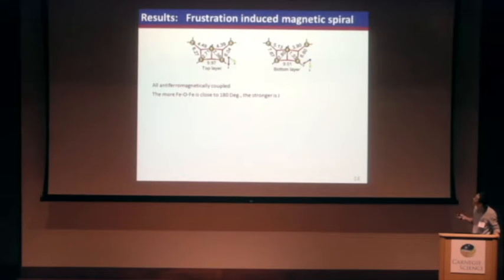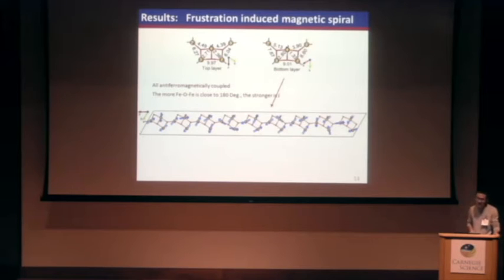It is found that they are all antiferromagnetically coupled. And the more this angle is close to 180 degrees, the stronger is J. The most interesting is that the specific structure and the antiferromagnetic coupling results in a spiral magnetic ground state. This is a period of 9 unit cells.